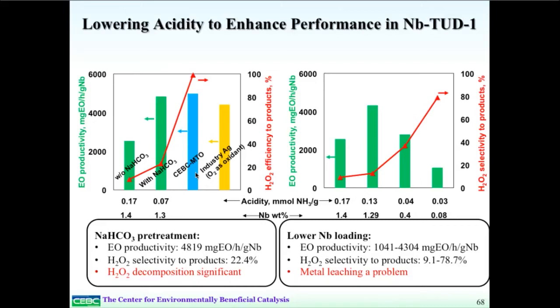We still have some issues with the decomposition of H2O2. You can also decrease the acidity by decreasing the metal loading. If you decrease the metal loading, you can get up to about 80% selectivity of hydrogen peroxide towards the products. And so the question is how do we combine these? In this particular case, you actually have more problems with metal leaching. So this is where computational chemistry comes in.